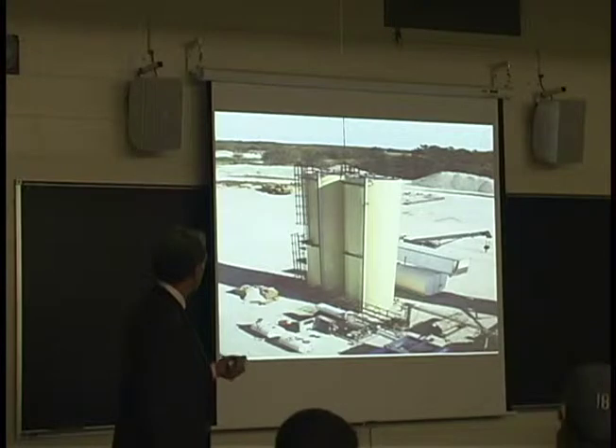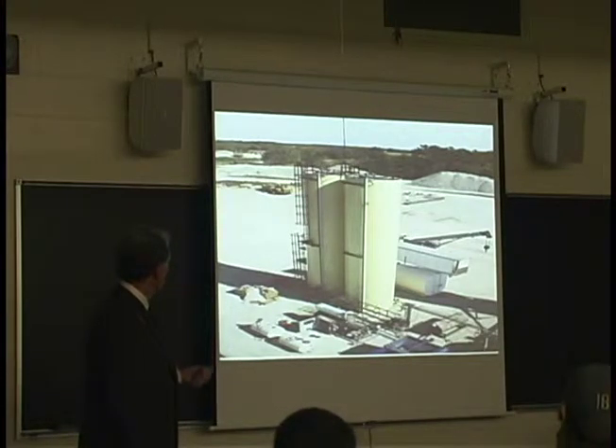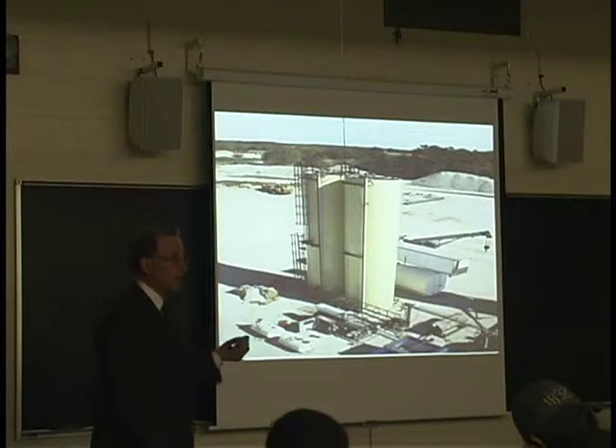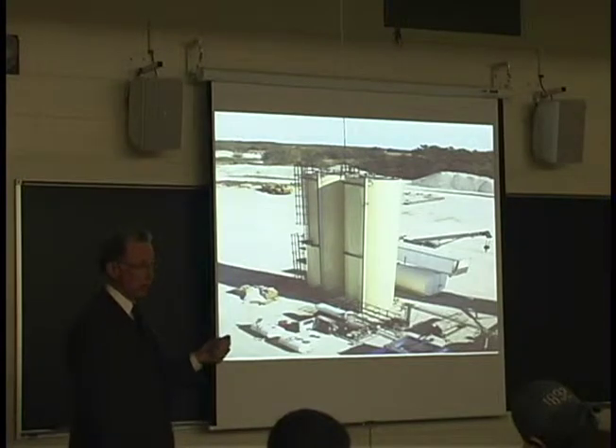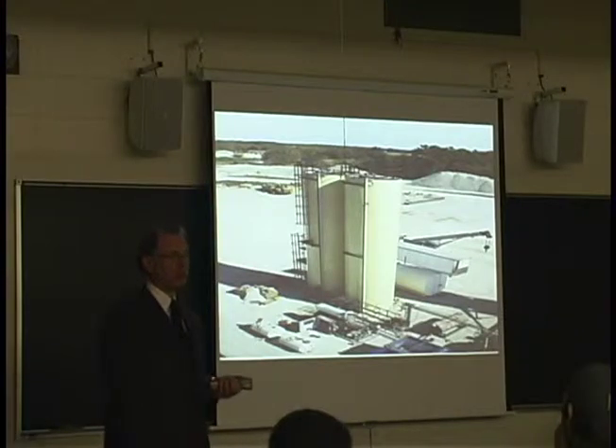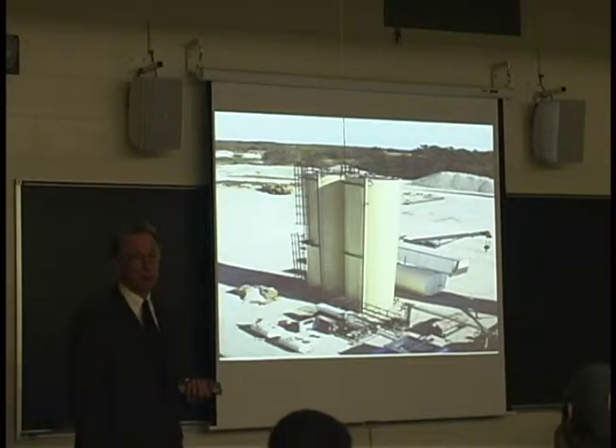This is liquid asphalt storage tanks. These are vertical tanks, and the material comes into our plant at 350 to 450 degrees. We pump it into the tanks. They're heated, they're insulated, and then it's ready to be used. If you let it cool off, like we'll have some in there over the winter, and we'll have to heat it up for next spring, I think my people tell me it takes about 4 gallons of fuel oil for about every 10 degrees that you want to raise that liquid asphalt. So it becomes an extremely expensive proposition.